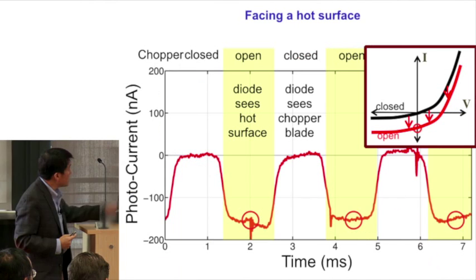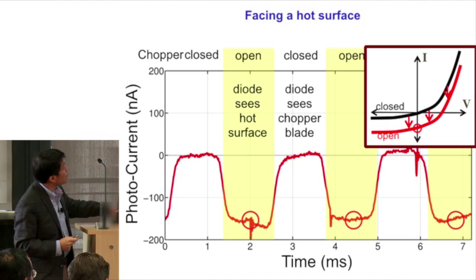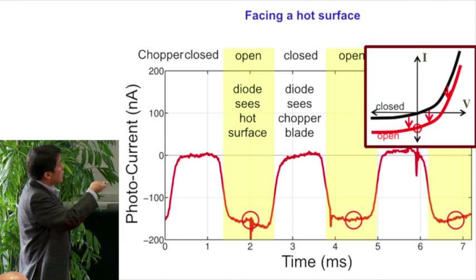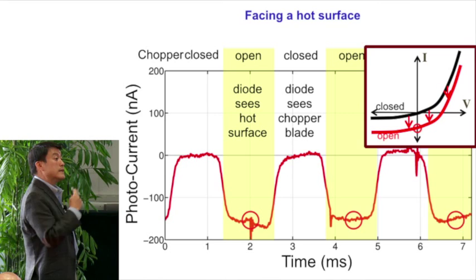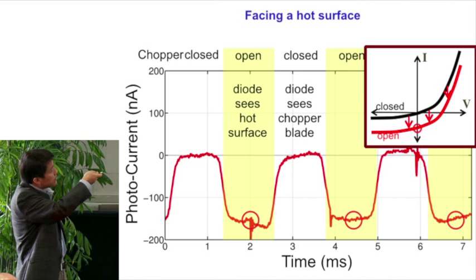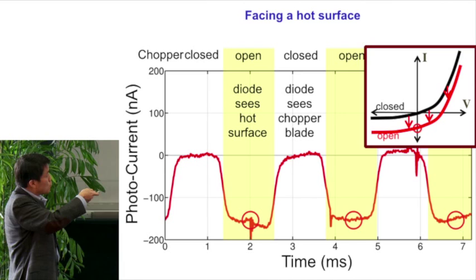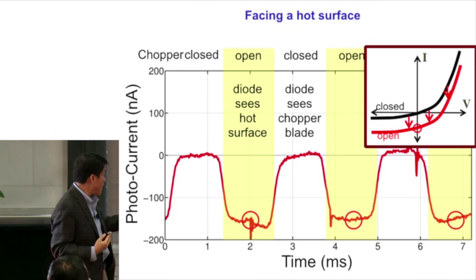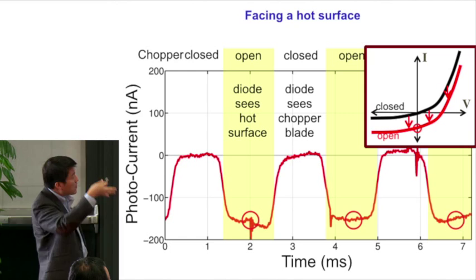So in the case where it's facing a hot surface, as the chopper rotates, we look at the photocurrent as a function of time. When the chopper blocks the light trajectory, you will have zero current. And then when the diode actually sees the hot surface, when the chopper is open, you will have a reduced current and therefore a negative current. Okay? And that's the typical photovoltaic operation mode. And that basically corresponds to the shift of the IV curve into the fourth quadrant.